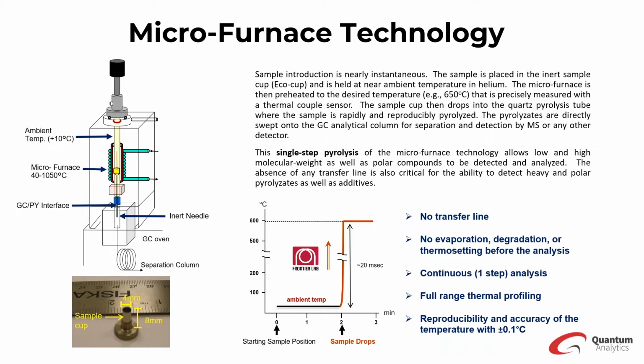The sample cup is only dropped into the furnace when the furnace is heated and ready. So this means there's no degradation, evaporation, or thermosetting before analysis occurs. This is a true pyrolysis reaction, and this furnace reproducibility is plus or minus 0.1 degrees Celsius, and it is precision measured. So that means when you're controlling that furnace temperature remotely, you're actually pretty close to controlling the sample temperature as well.